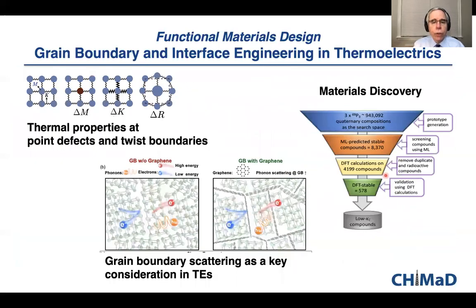And so the focus of this group has been twofold. One is to focus on grain boundaries and interfaces to understand how these affect things like the thermal conductivity and the thermal diffusivity in the material, both in terms of twist boundaries, the actual boundaries, the structure of the boundaries between two crystals. We've also worried about what the effects of graphene and the graphene boundaries are on the scattering, and hence how that affects the thermal properties.